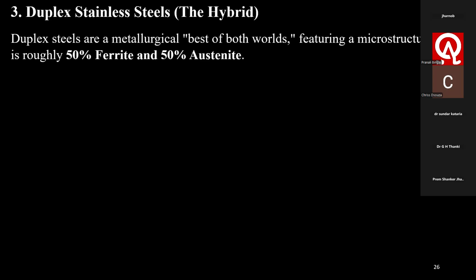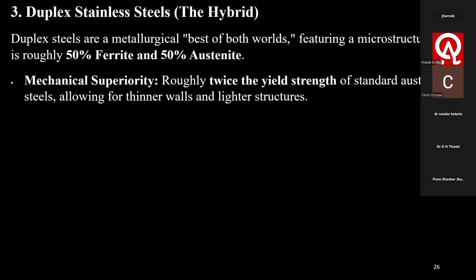Next comes the duplex stainless steel. That is what we call hybrid. Duplex steels are a metallurgical best of both worlds, featuring a microstructure that is roughly 50% ferrite and 50% austenite. Mechanical superiority: roughly twice the yield strength of standard austenitic steels, allowing thinner walls and lighter structures. That means, from the cost point of view, it also wins the race.